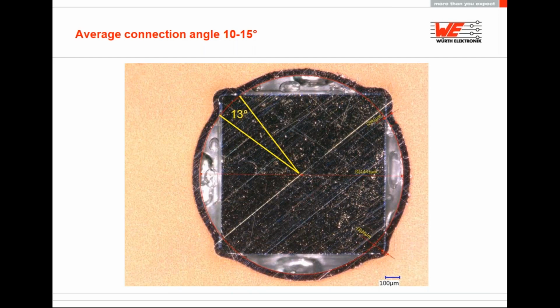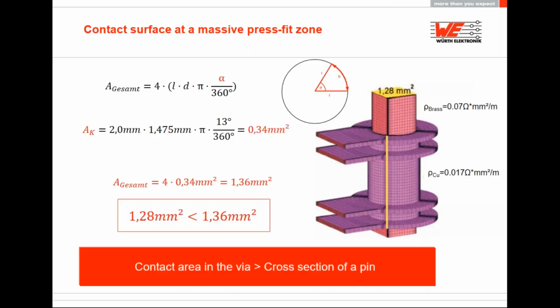And so in this image, we can appreciate the average connection angle of the massive pin. Normally, on average, we get about 10 to 15 degrees of connection angle, but you can see that only the corners make contact with the PCB. But that is more than enough, and you'll see why in this next slide.